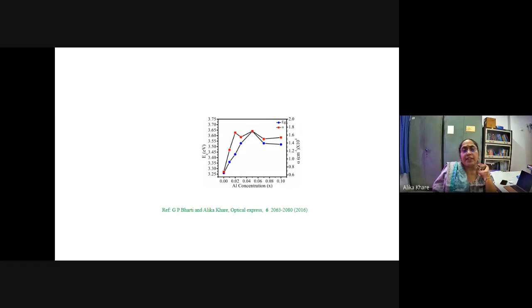One could see that with increase in aluminum concentration into ZnO, the band gap has increased. But after attaining some optimum value, it has fallen down, because with a large quantity of aluminum, it was becoming conducting, and that is why the band gap has fallen down.